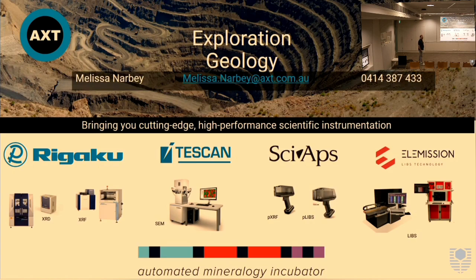Sorry, so with LIBS, you do one spot, and you do several laser firings on that spot? There are different ways of doing it. With our handheld instrument, which is used mainly for quantitative chemistry, you can drill down on the one sample, up to 20 or 30 different zaps on the one spot. We find for minerals 3 is adequate, and then it rasters over a 12-point area. With this technique, you can do a cleaning shot, but we find that we don't tend to. If you had a very dusty material, you'd probably want to, but we try and clean up the core first.